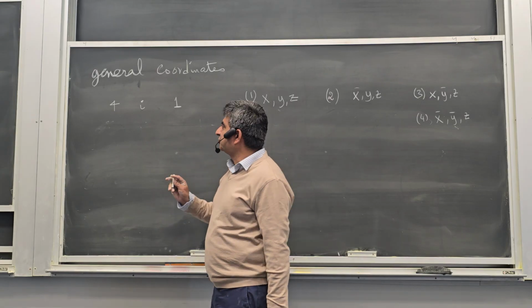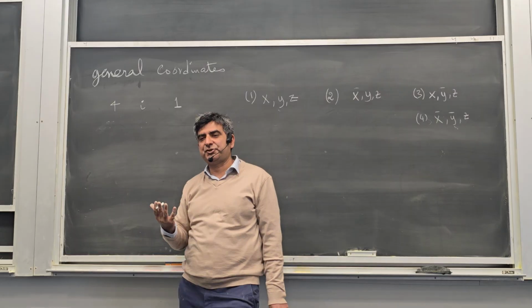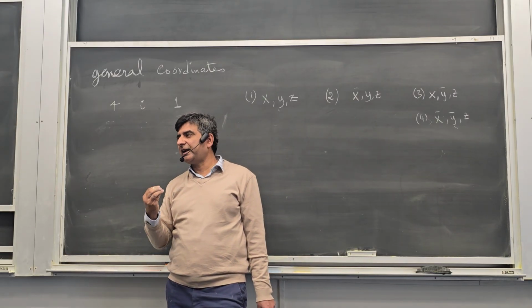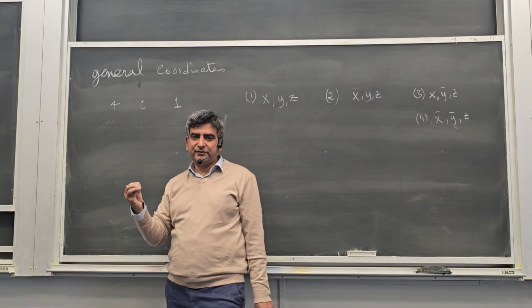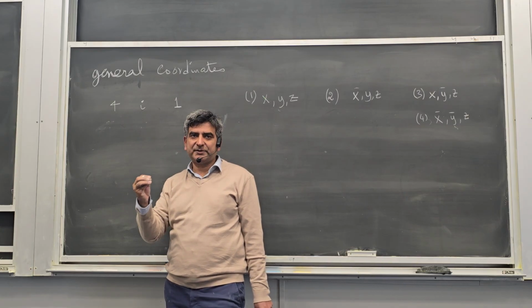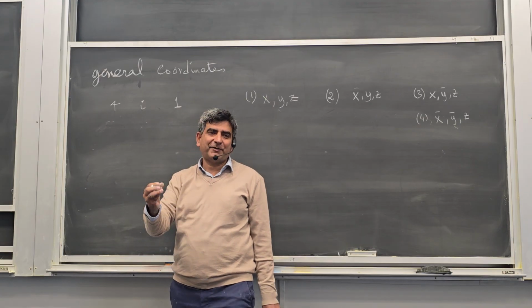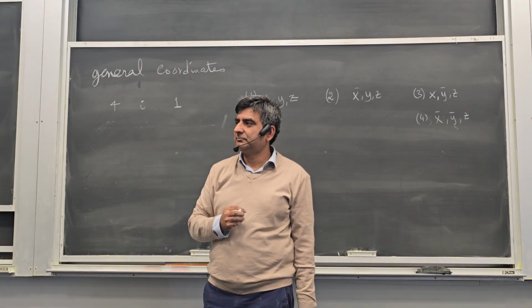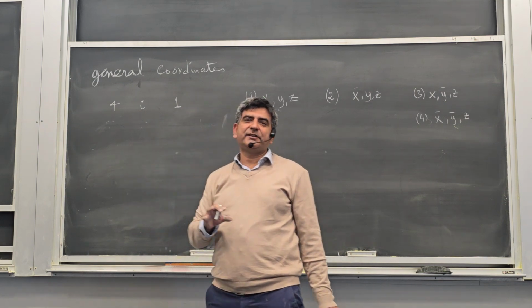The position of these 4 atoms is generally called the 4i position in the P M 2 group. So if an atom exists on these 4 locations, the same atom must exist on these 4 locations. So you say that the atom is on the 4i position. This is the most general position in this space group.